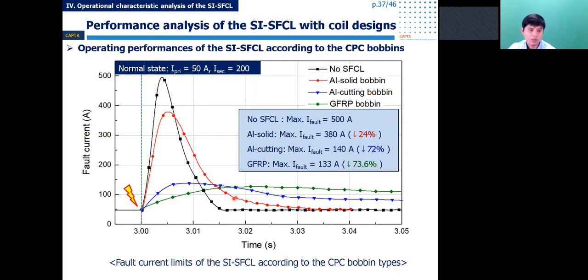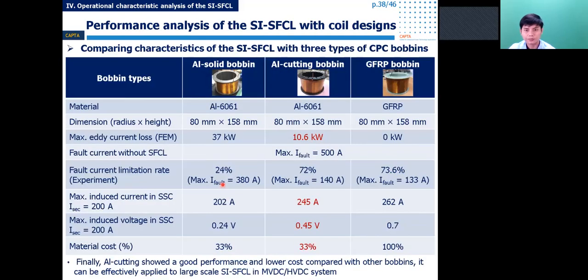However, the GFRP bobbin could reduce the current rising di/dt better than the aluminum cutting bobbin. So it can increase the fault limitation time compared with the aluminum bobbin.